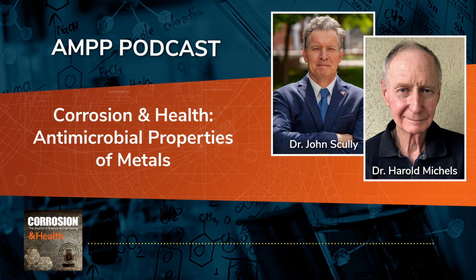But the most recent work that I can find that referenced copper was basically, during a cholera outbreak in Paris in the 1860s, they found out that copper workers, which I assume they mean coppersmiths, were not impacted by cholera, but the general population was. So there are lots of reports. There's a famous Roman surgeon that had very low infection rates, and he used bronze instruments, which was quite common in that era. So there are things in history where people have used it, but this was before the germ